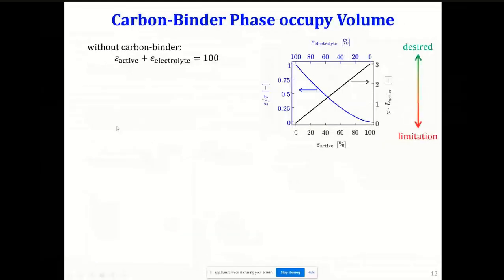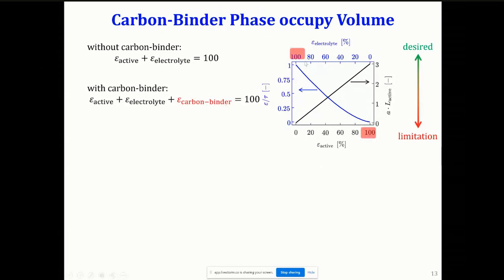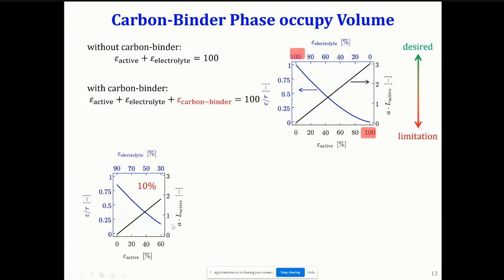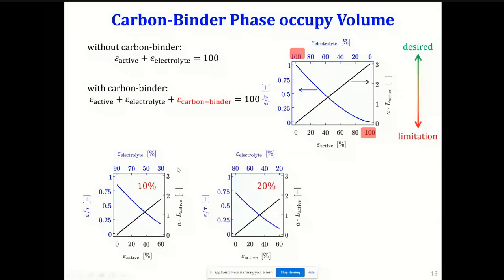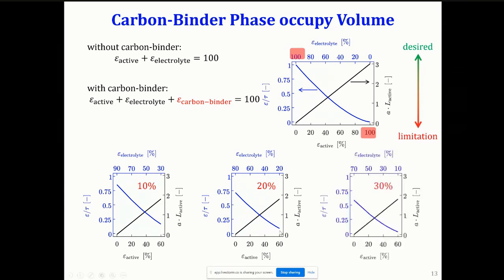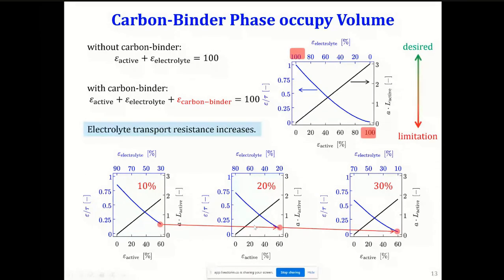Previously, only the active material and electrolyte were making up the total volume. Now, once we add the third phase, we are cutting off the excess on either side. And what that would do is shrink these windows, and not in a helpful way; it will shrink the windows in the opposite fashion, because it will cut off the part of active material which gives higher area. It will cut off the part of electrolyte that gives you lower resistance. So if you have 10% active material, this is the window you're looking at. Now your 60% limit plus 30%, and the rest is 10%. If you go to 20% carbon binder, and all numbers are by volume, then you are making it even worse. If you go and add 30%, it's even worse. And you see this gradual decline trend. As you are going down and down, it means your electrolyte transport resistance is increasing.